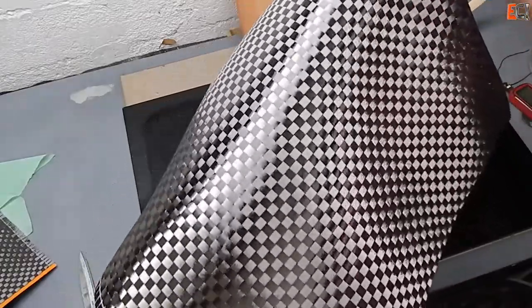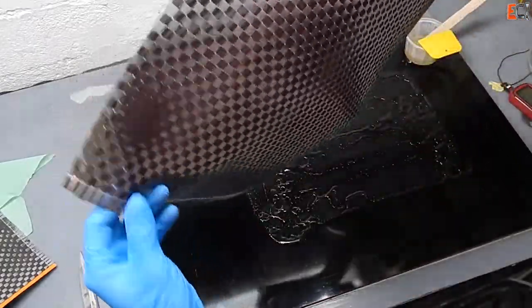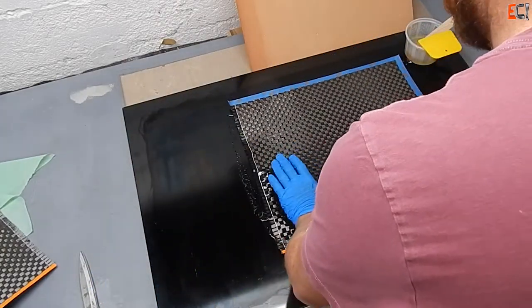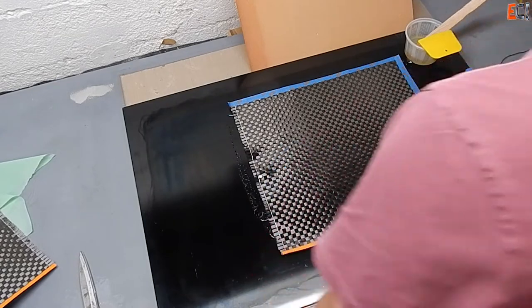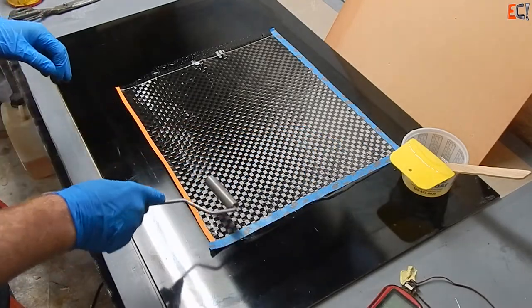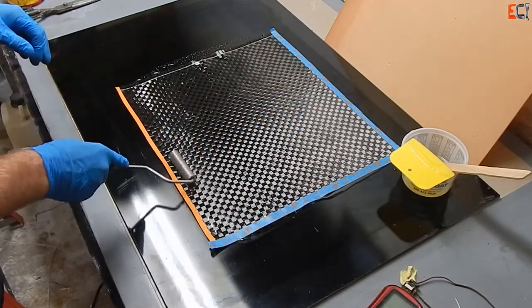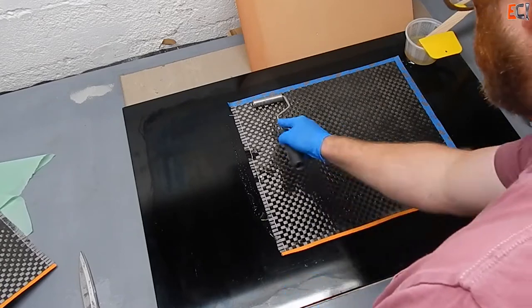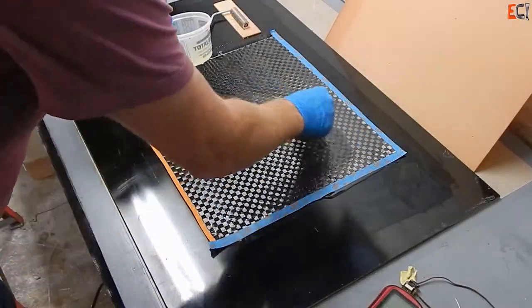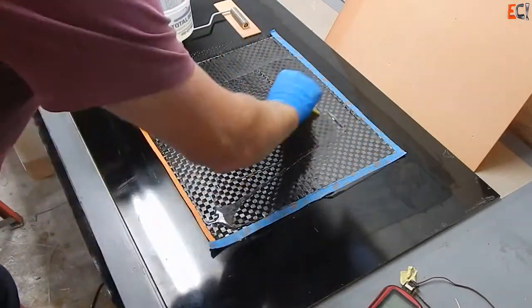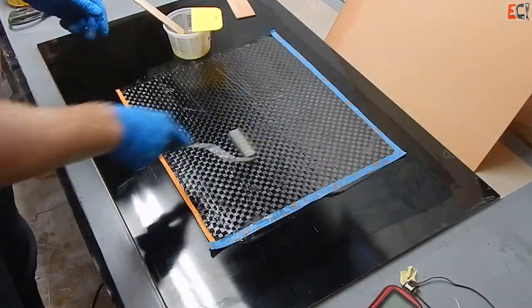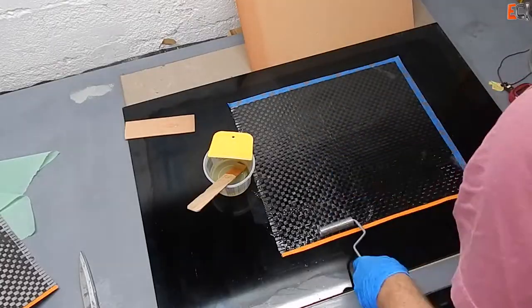So here's the spread tow going down. This is 185 gram, roughly 6 ounce carbon. This is a Hexcel product, a couple of other companies make spread tow. It's generally a little more expensive but it's thinner and has better mechanical properties because there's less crimp as the fibers go up and over each other. They do so less often because the tapes are wider and because the tapes are thinner they don't have to go up and over each other quite so much.